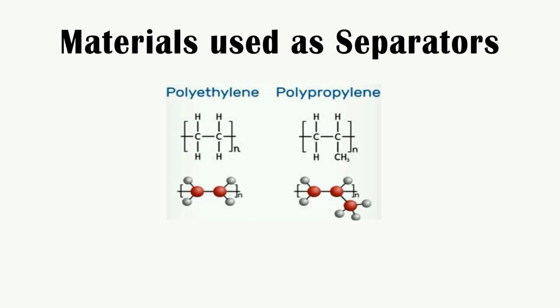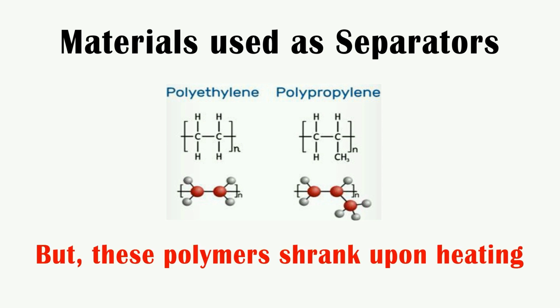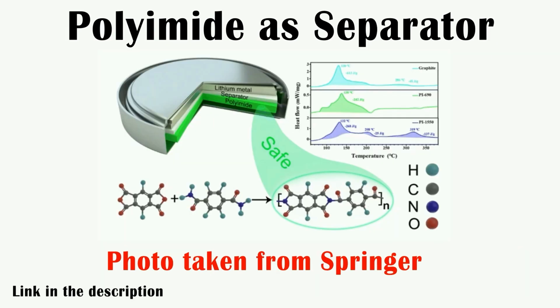Currently, polyethylene and polypropylene are used as separators in the lithium-ion batteries. But the problem with these polymers is that upon heating, they shrink and may be unable to prevent the direct contact between the cathode and anode. So, thermally stable polymers like polyimide can do this job better in replacement of the polypropylene and polyethylene.